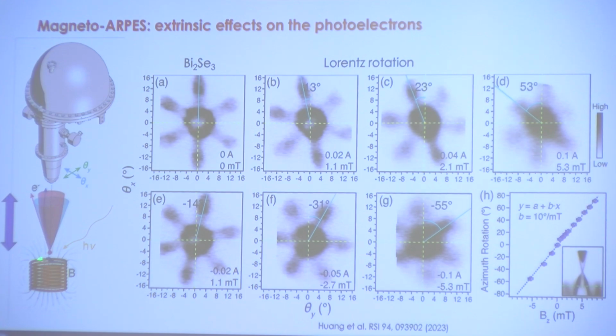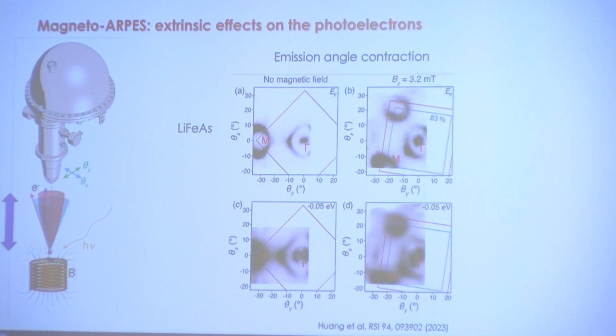Again, these are effects that are not directly on the electronic states, but just in this region where we have modified, we need to figure out how to reverse these effects to figure out what is the initial state from where the electrons were ejected. So we tried on bismuth selenide, and these are constant energy contours taken here below the Dirac cone. As you crank up the current, you crank up the field, and then you see naturally there's a Lorentz rotation, and this is actually a nice way to tell us exactly how much field the sample experiences. And you can see that it is a linear behavior as expected, so this is an effect that's easy to reverse.